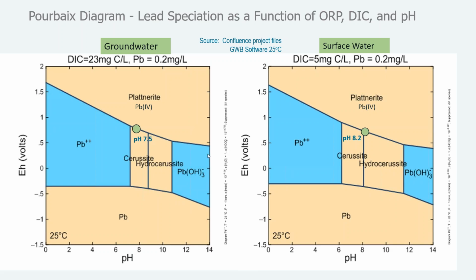And for the groundwater system, we predict that we would be forming cerussite and some plattnerite. This is the more highly oxidized form of lead. As we move up here, we're in more oxidized forms. Lead 4 is great. That's the least soluble form of lead, and if we can form it, we certainly want to try to. Whereas in the lower DIC surface water, we'd be forming some sort of mixture of hydrocerussite and some plattnerite would be predicted. So maybe this helps explain why Tacoma's lead levels were so low in last monitoring when they were able to have higher pH and more chlorine, and why we're seeing pretty low lead levels coming off of those pilot rigs as well.